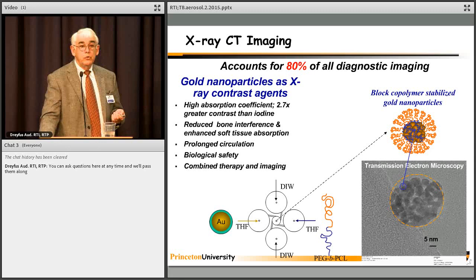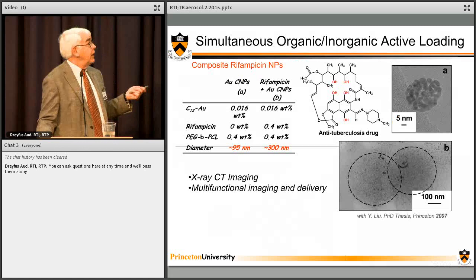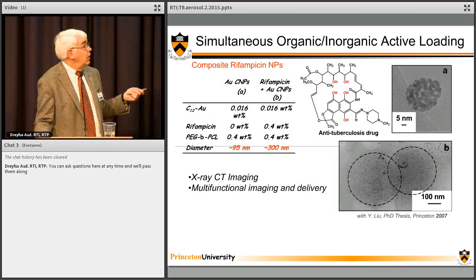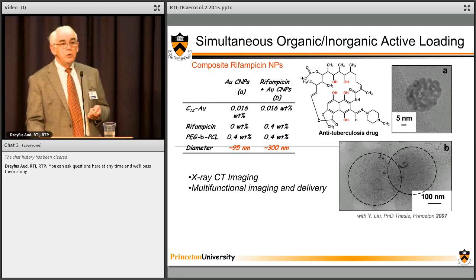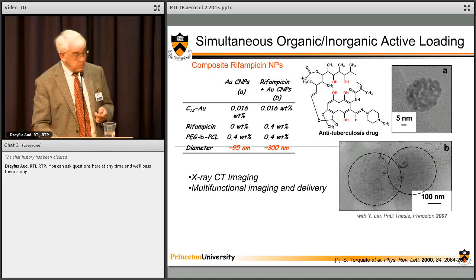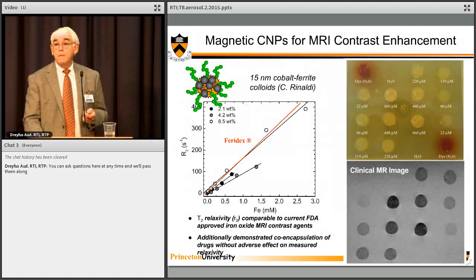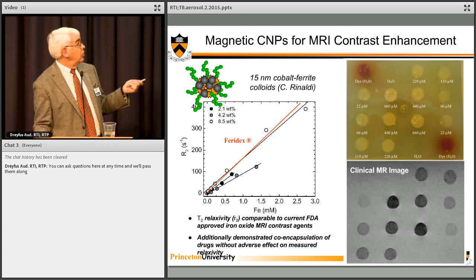And you can also now co-incorporate drugs in these gold particles. This is rifampicin, a TB drug. This is a material without any organic. This is with rifampicin, so it makes slightly larger particles here. The small black dots are those gold particles, and people in the X-ray community say they could see this. That's a high enough density of gold that they could see these nanoparticles in animal imaging. So we can deliver organics and imaging agents. A more interesting one is actually to take small colloidal 15 nanometer cobalt ferrite colloids.